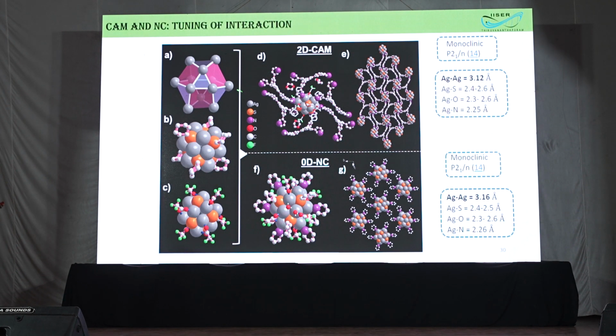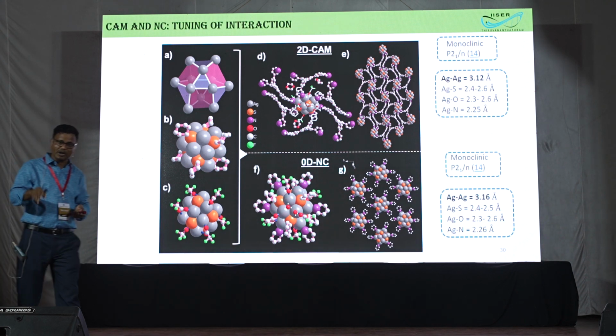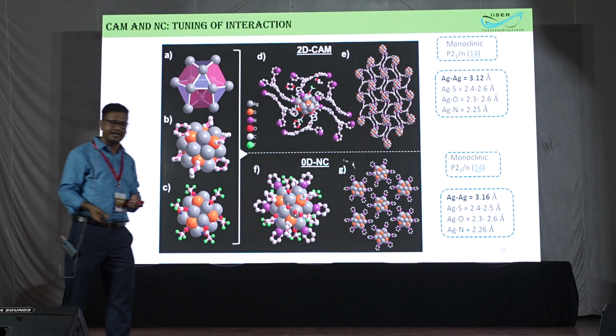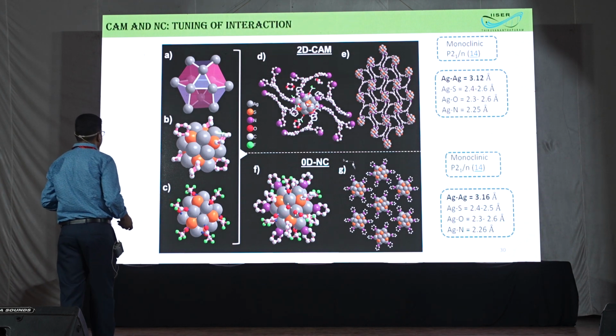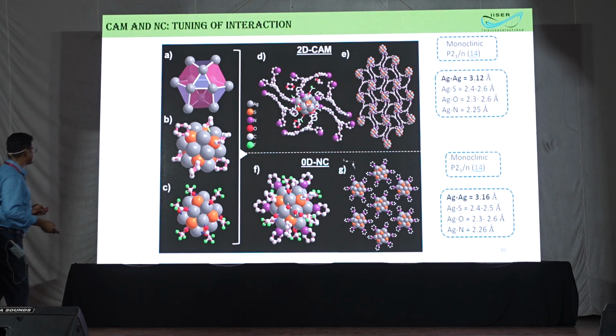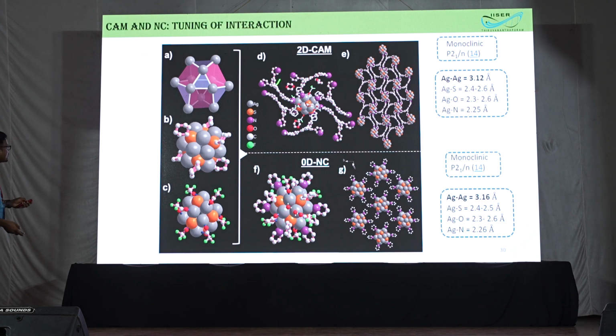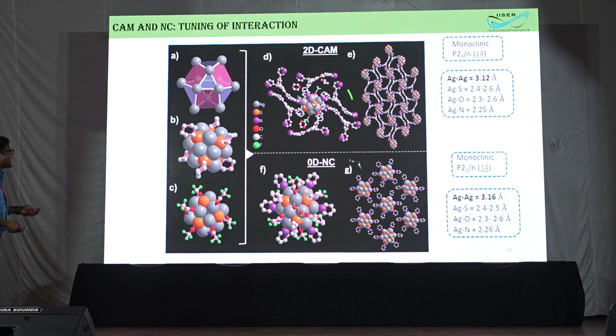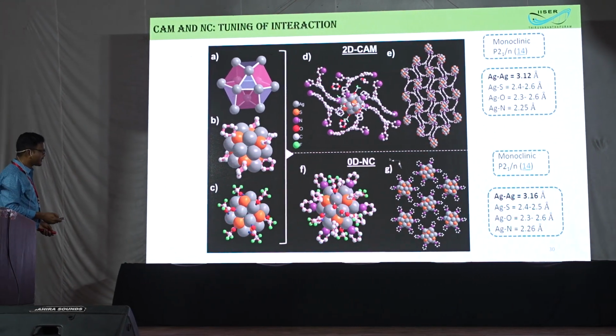Very recently we have tinkered, because in those cases we were only thinking of Ag12 linked by azopyridine. We have synthesized a molecular cluster. This is very difficult: small is very difficult because of the stability. The Ag12 cluster we protected with pyridine, and another cluster we protected with a big tripod linker with nitrogen ether. This is the molecular cluster in the solid state, and this is the two-dimensional structure.